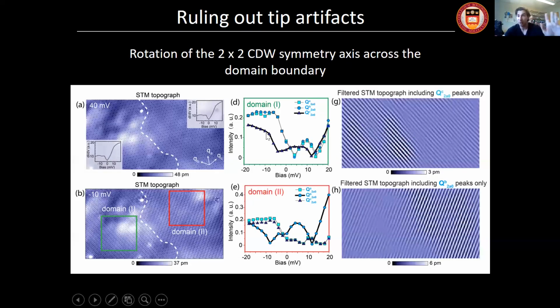So again, just to convince you, this is not our tip. We can image a domain boundary. These are not often found for this 2x2 charge density wave state, but we can occasionally find something that looks like this on the left. The domain boundary at 40 millivolts STM topograph might be harder to see compared to -10, but at -10 you can clearly see something's different here compared to the other side.